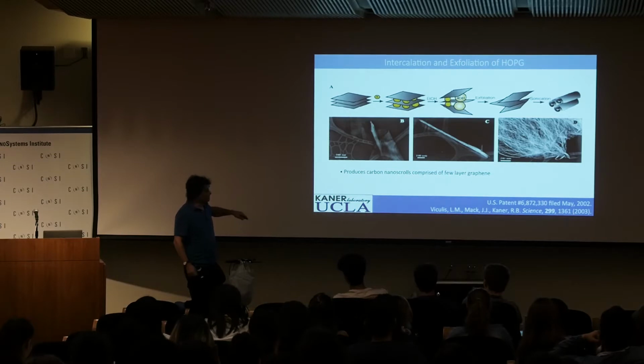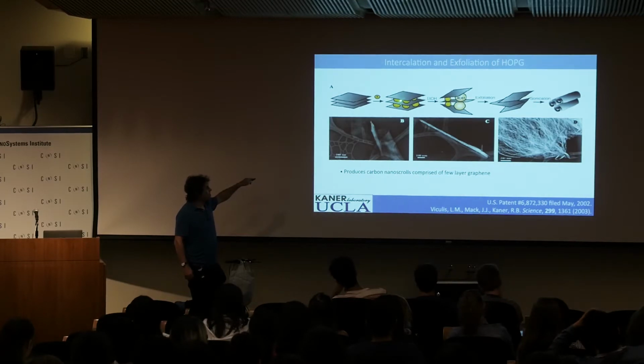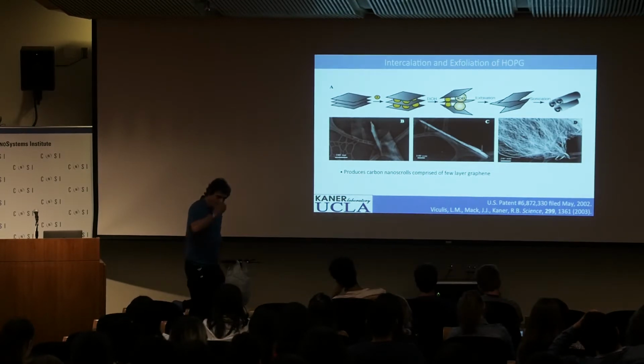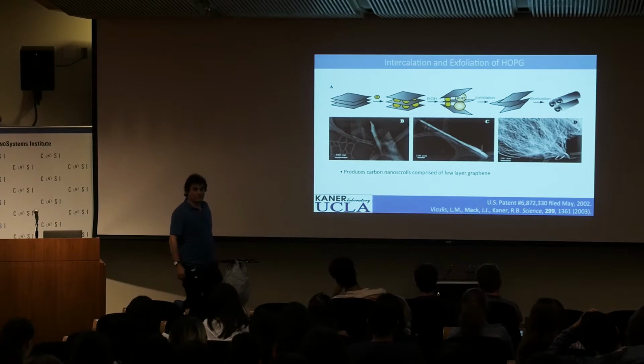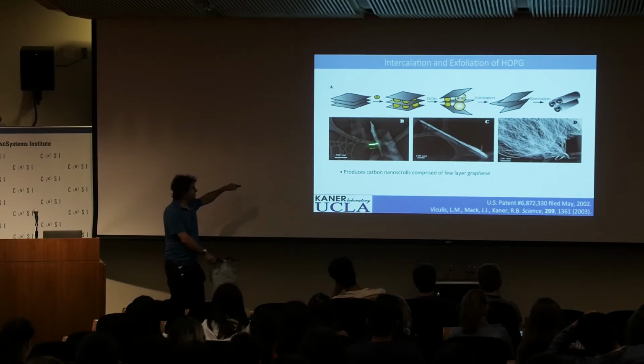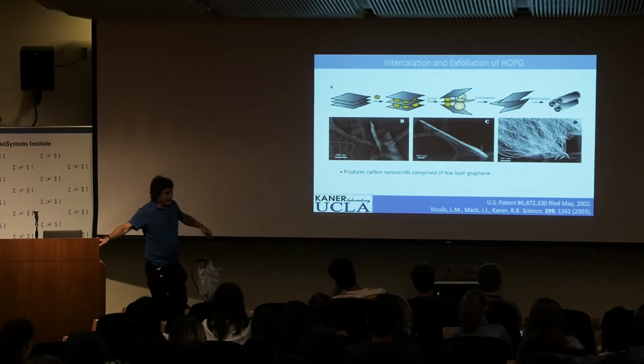It's air sensitive, so you do this in the absence of air. But we made what's called a first stage intercalation compound. So for every layer of carbon, there's a layer of potassium plus. We also know that this is incredibly reactive, so we just hit it with alcohol or water and blow the layers apart. And after we did that, this is a transmission electron microscope picture. And this is what we created.